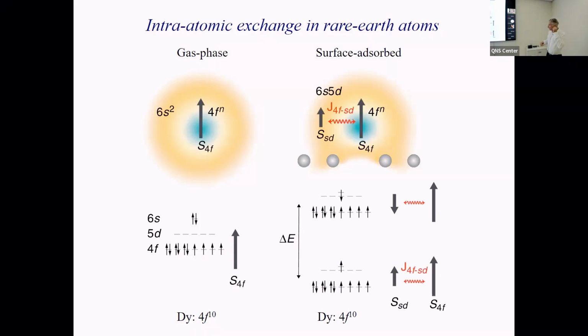And we have basically a model which is a little bit more sophisticated. So the good quantum number, from our point of view, is something which combines this moment that comes from the 4f shells with the moment that comes from the outer shells. Now, if you come up with such an idea, you have to know how strongly they are coupled, because inside the atom they have some coupling, and this coupling seems to be relatively strong.